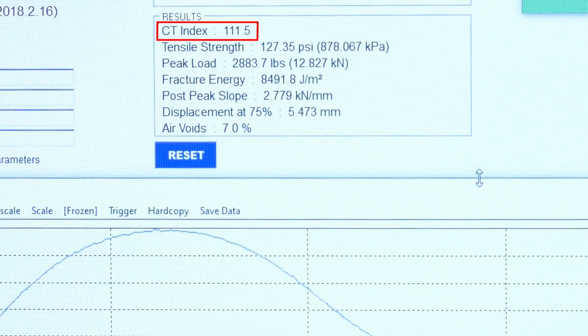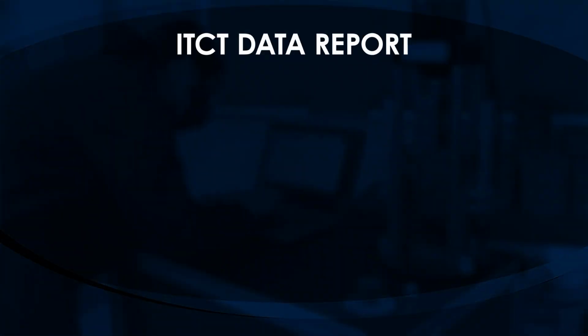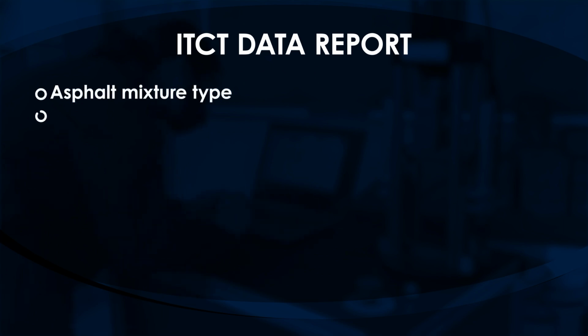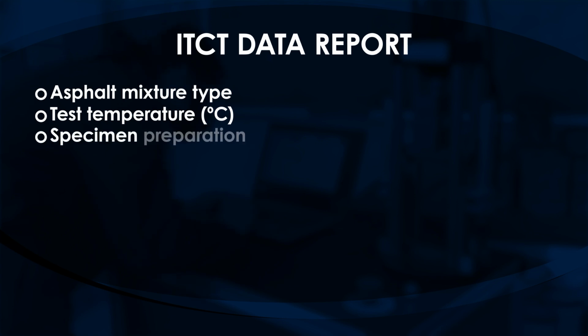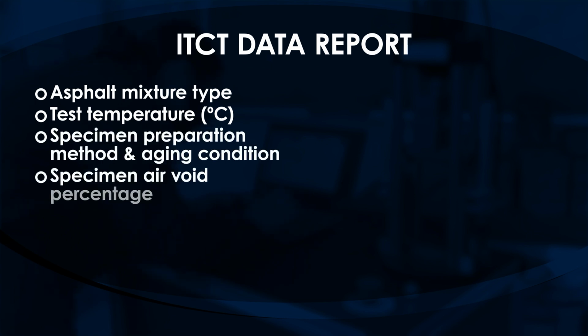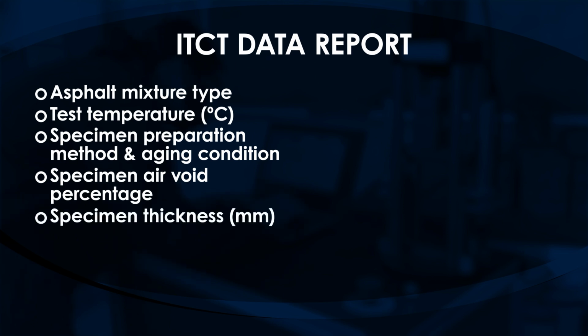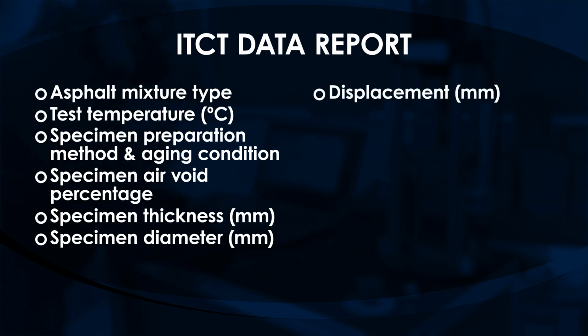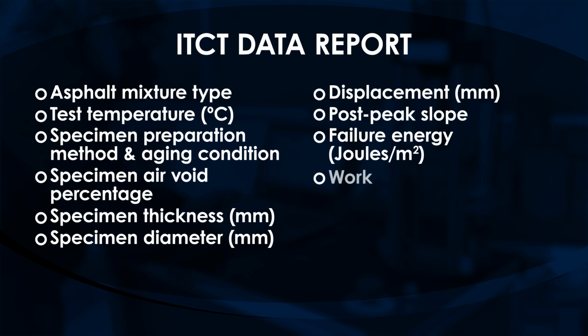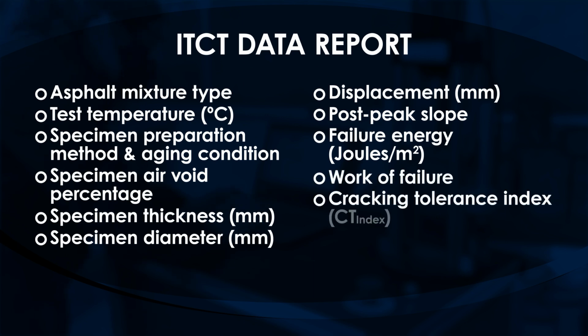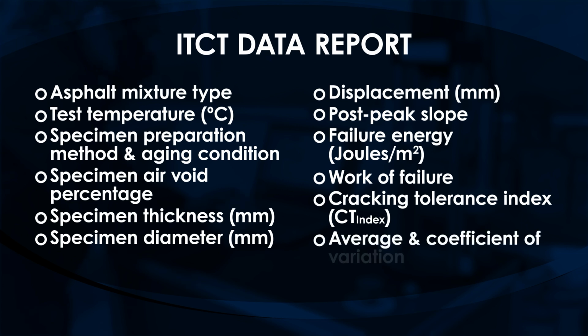Analyze the test data and calculate the cracking tolerance index, or CT index, as described in the standard. An ITCT data report may include the following parameters for each test specimen: asphalt mixture type, test temperature in Celsius, specimen preparation method and aging condition, specimen air void percentage, specimen thickness in millimeters, specimen diameter in millimeters, displacement at 75% of the peak load after the peak in millimeters, post-peak slope, failure energy in joules per meter squared, work of failure, cracking tolerance index, or CT index, and average and coefficient of variation in percent of CT index values.